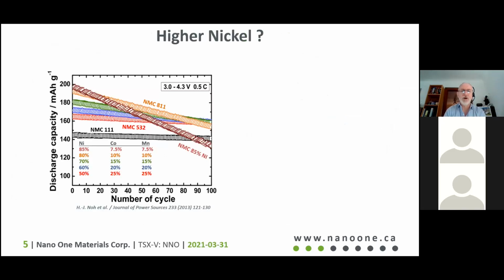So why go to higher and higher nickel? The NMC for long-range electric vehicles is pushing to higher and higher nickel. And this graph here explains it quite clearly. The black flat line here is nickel, manganese, cobalt in equal proportion, 111. And it's pretty flat. The capacity is low, about 145 or so, but it's very stable.